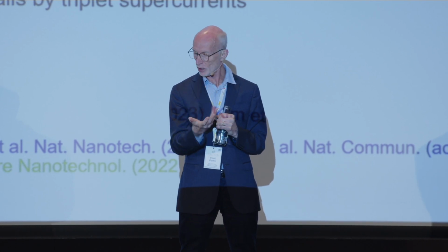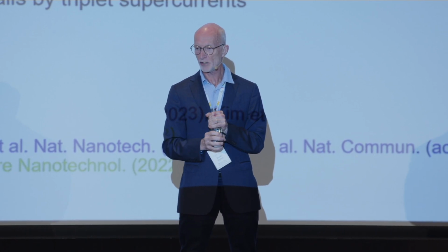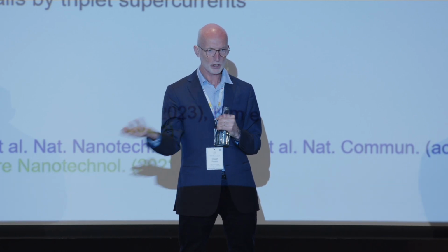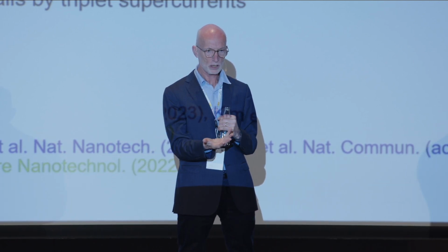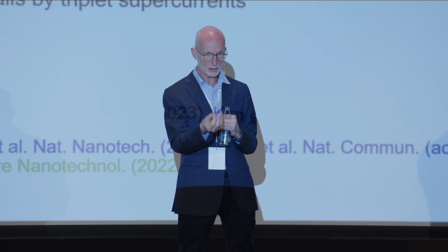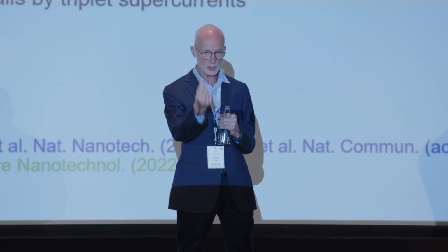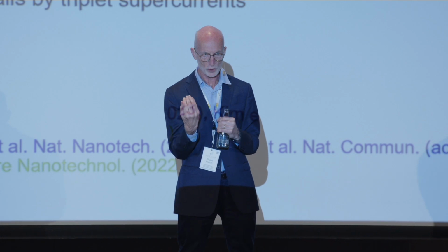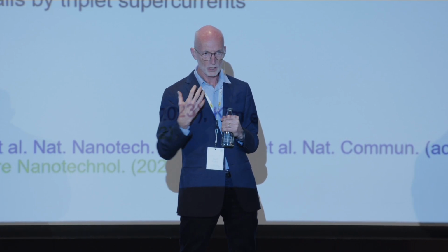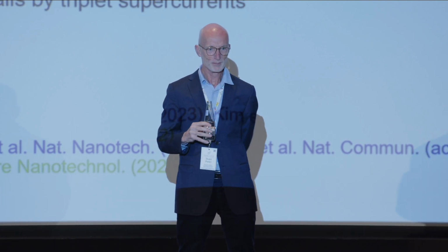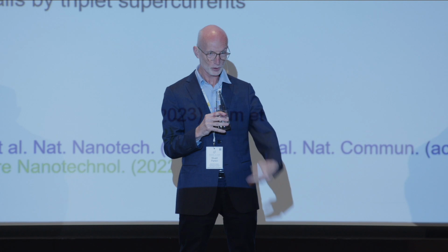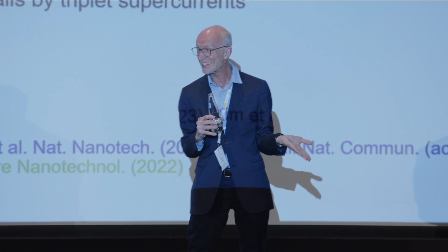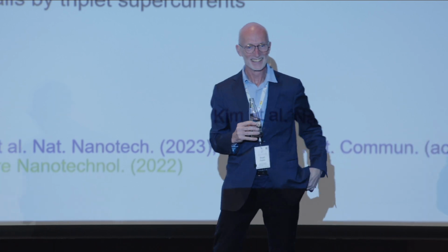So in other words, you're totally right, but let's say we take a spin valve sensor that is used in all the disk drives manufactured in the world since 1997. That uses a ruthenium layer which is 7 angstroms thick. It uses interface layers of cobalt 1 or 2 angstroms thick, already used. You're talking about 1 angstrom thick? 1 to 2 angstrom. So what's the difference? It's the same, right?